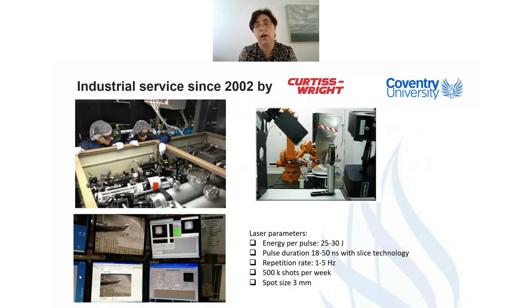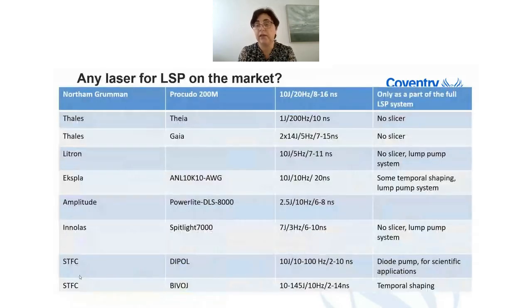Their laser system has a pulse energy between 25 and 30 joules. I think they even have a laser up to 50 joules. Pulse duration they can vary between 18 and 50 nanoseconds, and they have this slicing technology for temporal beam shaping. They are using a repetition rate between 1 and 5 hertz because their laser is a so-called lamp-pumped system. And being very advanced in laser technology, they know that those lasers can sometimes be unstable. This is why in the picture at the bottom left you see screens showing the monitoring of every laser pulse, both after the laser and also on the material.